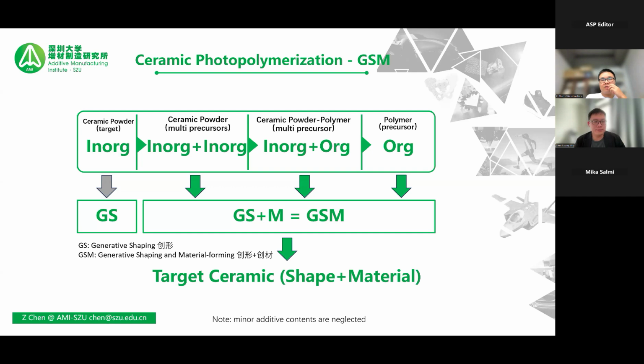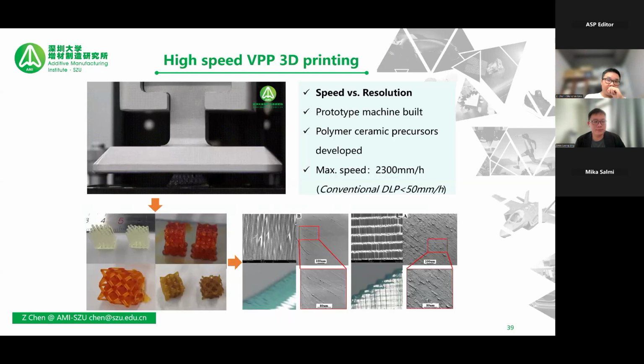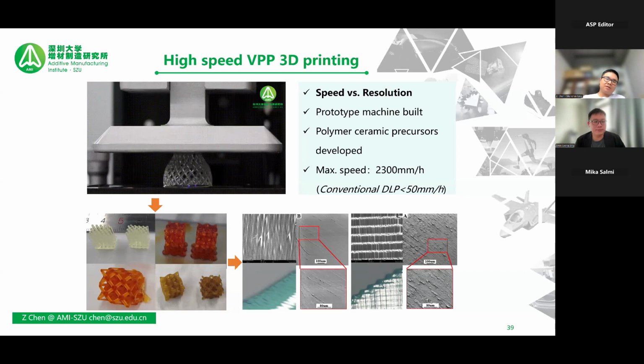And we also produce our high-speed VPP 3D printing. You can see that it's like click, okay, with the underlying mechanism being the photo inhibition strategy. Then we want to use this kind of method to produce, firstly, the commercially available resin, and secondly, the PDC precursors. And then we try with the slurries, of course, because the slurry is very difficult with high viscosity, and the viscosity increases from the resin, to PDC precursors, and then the slurry. So with the increase of viscosity, the difficulty is also augmented for this kind of technology. Well, there are some benefits, of course.